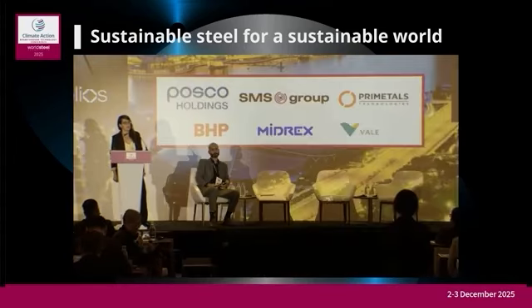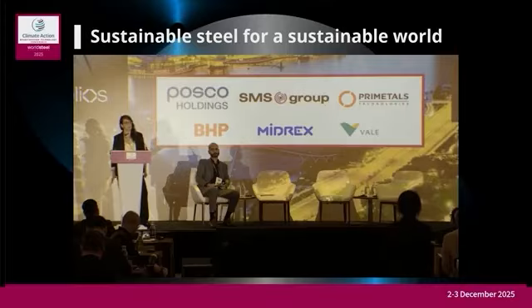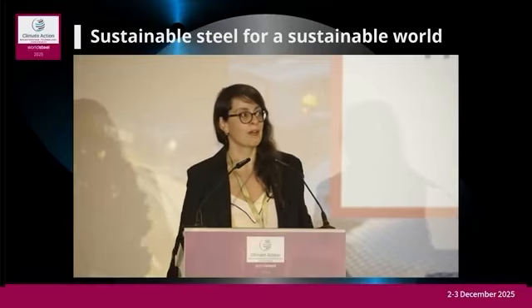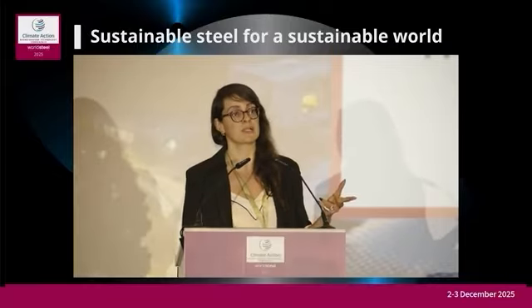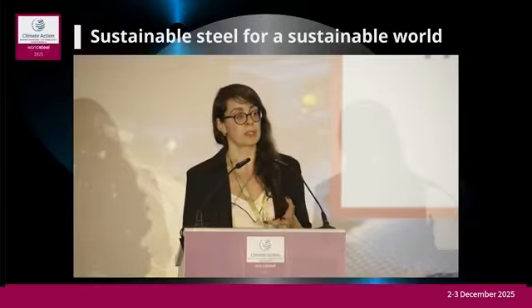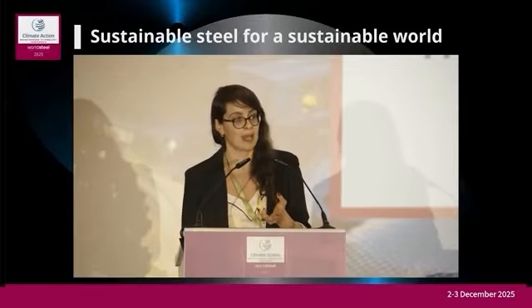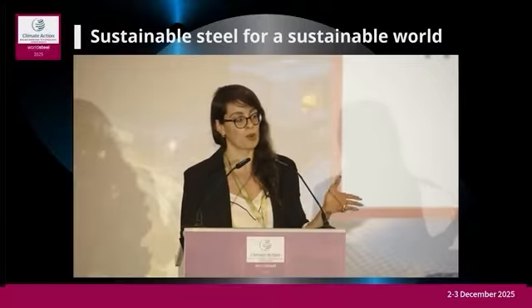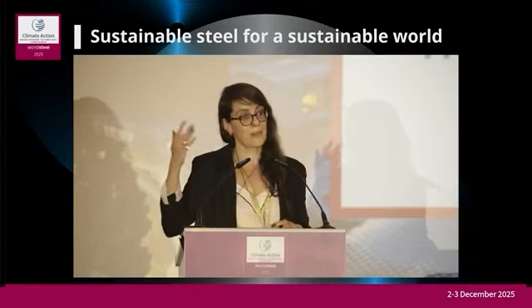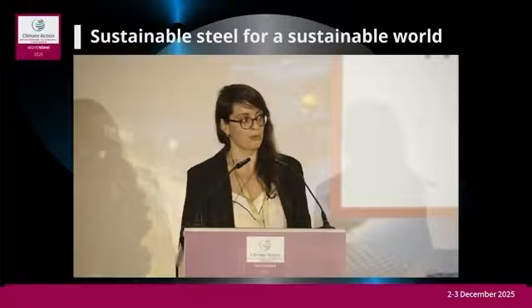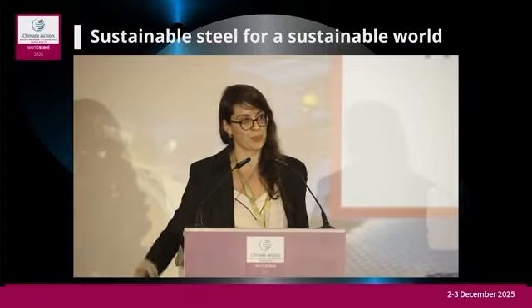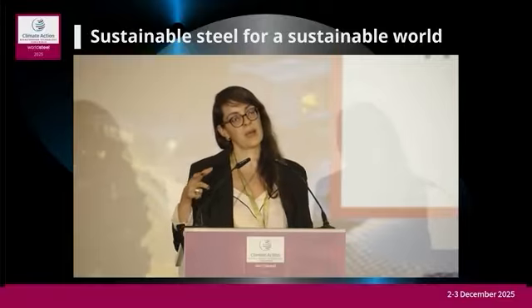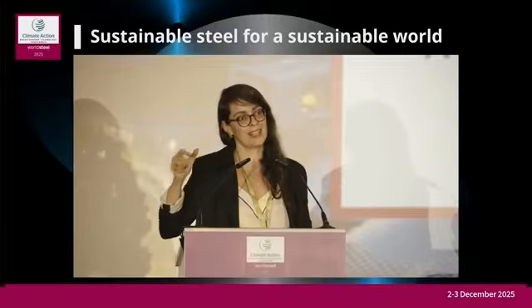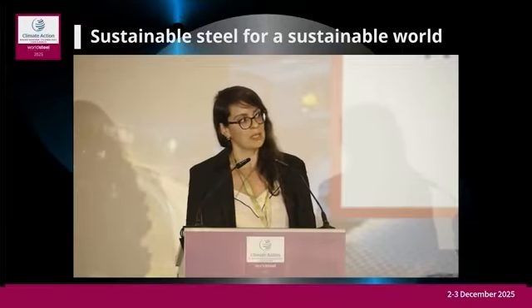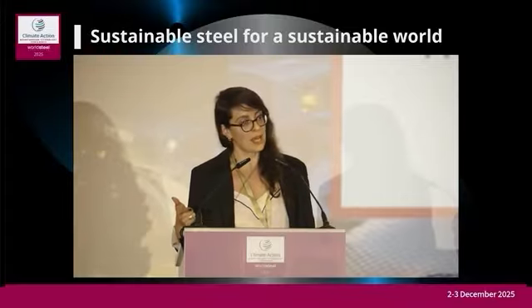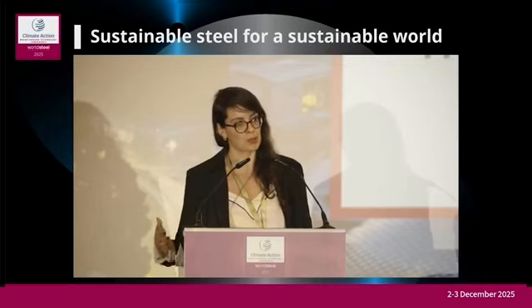Yeah, particle size. We evaluated at this stage up to 10 millimeters particle size, and we demonstrated that there is no difference, meaning tailings, for example, are a really fine powder, and we also started with run-of-mine material, which we ground up to 10 millimeters, and the kinetic model shows that there is no difference in this range. What will happen with a bigger particle size, it's a question, and of course, once we scale up even further to ton per day production, we will be able, in the unit itself, to have an input that is bigger than 10 millimeters. So it's all about the mixing process, the sequence of the addition of the material during the process, and controlling the temperature, as you said.